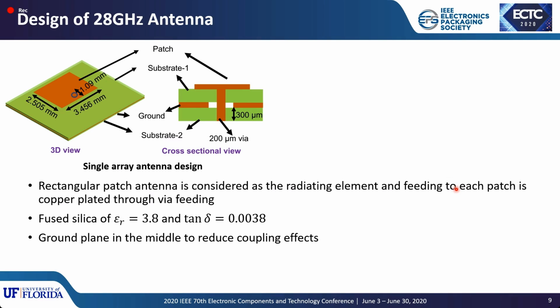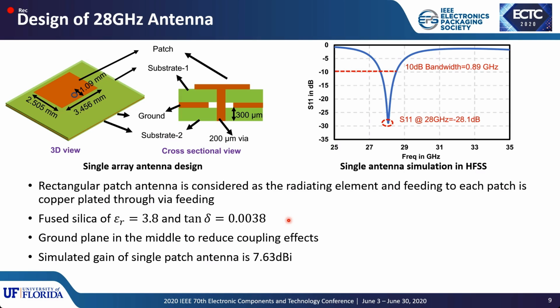Coming to the design of the 28 GHz antenna, in this slide you can see the design of a single patch antenna on two substrates. You have the top substrate and the bottom substrate, which are separated with a ground plane in the middle. The ground is placed in the middle of both substrates in order to reduce coupling effects. This design is on fused silica with a dielectric constant close to 3.8 and a very low loss tangent value. The return loss of this architecture is shown here. You can see the single antenna simulation from HFSS: the resonance frequency of the design structure with these dimensions is close to 28 GHz, the 10 dB bandwidth is equal to 0.89 GHz, and the simulated gain of the single patch is close to 7.63 dBi. Based on the single patch performance, we tried to design the 4x4 array antenna.